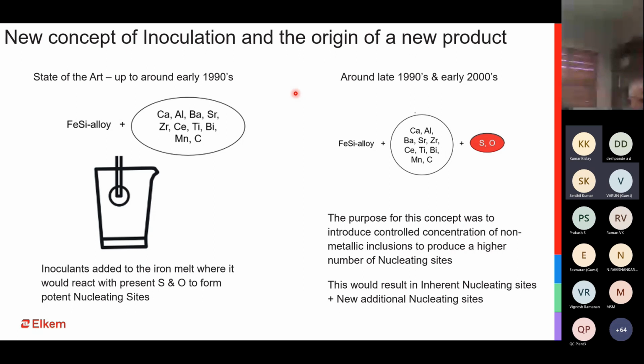So how do you bring the nucleation back? One of the ways is to precondition, of course, but the other way of doing it is if you have an inoculant which brings its own nucleating potential with it, and thereby gives you some additional nucleating sites along with the ones that you already have. So this was the concept because of which the sulfur and oxygen coated inoculants came into the picture, and that was the origin of this new flagship inoculant that we see in the market today.